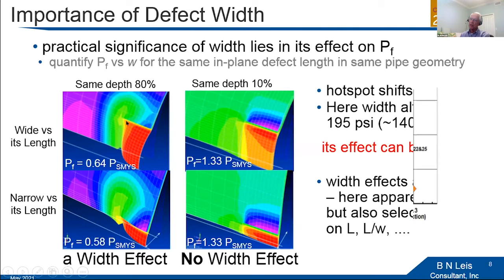And what you see here for the same depth, this happens to be a feature that's 80% deep. That's the maximum allowable by code. You see a difference in the failure pressure as a function of the width. That, in this case, amounts to 195 PSI. So there's a width effect for deep defects, but if you look at the same scenario in terms of length and width, but now consider just 10% depth, the outcome in terms of failure pressure is identical in both cases. So there's no width effect.